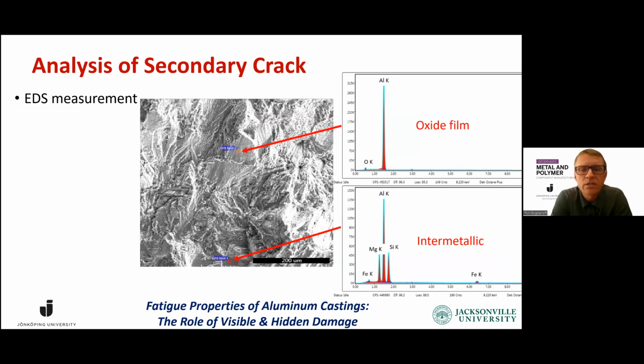And what we can find is that we have this brittle cleavage. We have some that is clear oxides and some that is intermetallic, that is expected. So we see that in the fracture surface and the fracture path, the oxides opening up are oxide films in this case, linking the fracture to the final failure.